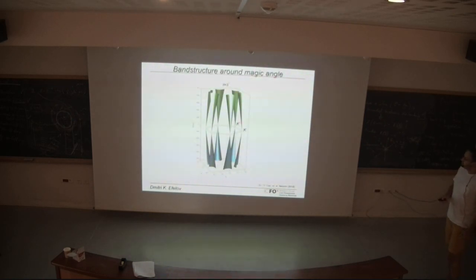Yeah. So if you look at the band structure, if I would follow this movie again, even from the single particle picture, the band structure between the hole and valence band is not symmetrical. So even without taking interactions into account, this would not be symmetrical. But then once we throw interactions in, and once these energy gaps start to become sensitive to the Fermi energy and how many electrons we fill in these bands, we're just not taking any symmetries into account. So we're not really expecting electron-hole symmetry.